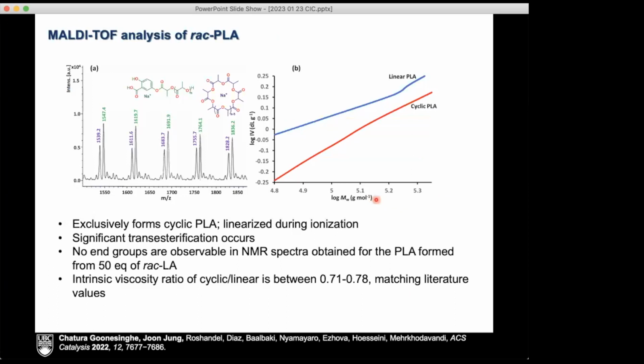And what Chatura finally found was that this was actually cyclic polylactic acid. We can tell that by looking at the MALDI analysis of low molecular weight material, where you can clearly see that you have cyclic material and open material that's been ring opened by the acid in the MALDI matrix that we're using.